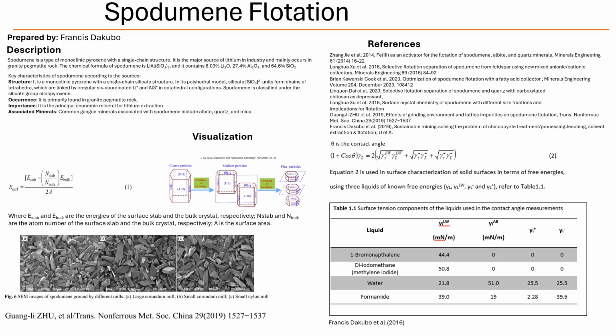Like what? Doesn't finer mean more surface area? It does, but remember the crystal planes. Ah, right. The 110 that collectors like versus others they don't. Exactly. Initially, grinding finer might expose more of the favorable 110 surfaces. That's good. But if you grind too fine, you might start creating a higher proportion of the less favorable surfaces, like the 001 basal plane. Because the crystal breaks differently when it's super fine. Potentially. Or you just get more edges and corners relative to the flat faces. Plus, very fine particles can cause issues like slime coatings or just behave differently hydrodynamically. It's complex. This idea of different faces having different properties is called anisotropic surface properties.